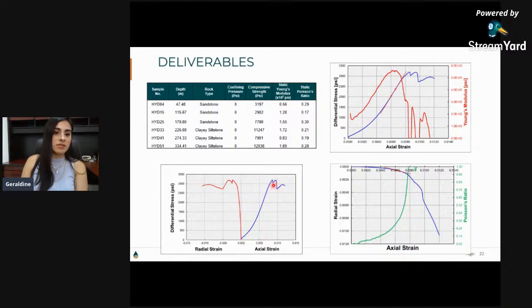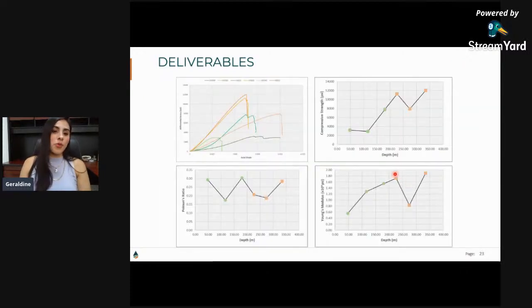Here, the blue line is the axial strain, and the red one is the radial strain. Also, you receive a plot that represents the Young's modulus and one representing the Poisson ratio. If your project has many samples, we compile all of these in a book where you can see the performance of each of these samples. Then also a graphic where you can see all the samples tested in one plot. This is the depth versus the compressive strength.